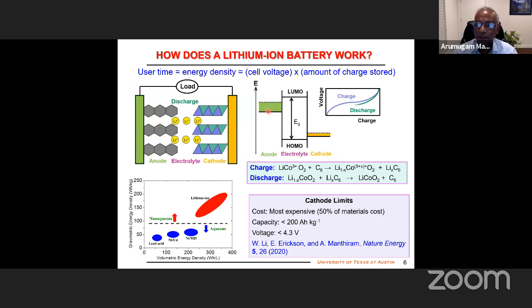I cannot keep on raising that. If I raise too much above the LUMO, then I'm going to have a problem, instability. In the same way, if this goes below the HOMO, there will be electrolyte instability. You see, the electrolyte is constraining the energy difference you can really make use of between these two electrodes.